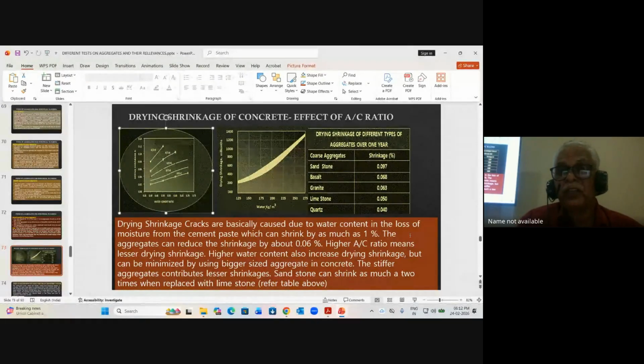The problem with shrinkage is that drying cracks are basically caused due to loss of moisture from the cement paste, which can shrink by as much as 1%. By using a suitable aggregate cement ratio, you can counter this and reduce the shrinkage significantly.